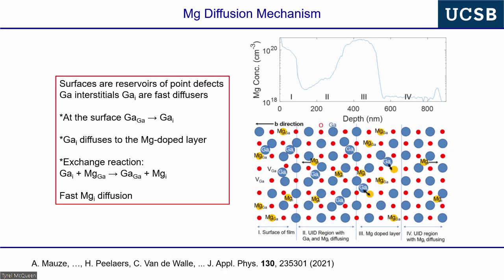Gallium interstitials are fast diffusers. And so what we proposed is that the surface is a source of gallium interstitials. Then we have gallium interstitials shuttling into the material. We have an exchange reaction at the surface with the gallium interstitial with the magnesium and the gallium. We have this exchange reaction, and then we have a fast diffusing magnesium interstitial. And this was borne out to be favorable in DFT calculations from Hartwin Peelers. And so that came out in a paper a couple of years ago in JAP that's referenced here.